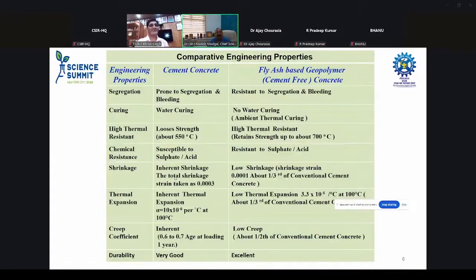Next, when we compare the engineering properties of geopolymer concrete, it is resistant to segregation and bleeding. It doesn't require water curing. It is highly thermal resistant. We have worked up to 700 degrees centigrade. It retains its strength up to 700 degrees centigrade, whereas cement concrete loses its strength at around 550 degrees centigrade. It is resistant to sulfate and acid. It has low shrinkage, low thermal expansion, low creep, and excellent durability.